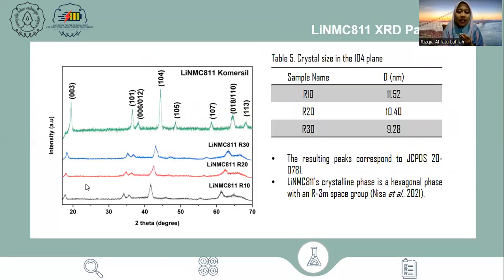The next is the diffraction pattern from the lithium nickel manganese cobalt material. The peaks correspond to JCPDS number 20-0781. The sharpest peak is obtained at 2 theta 41 to 43 degrees. The crystallite size obtained is presented in Table 5. The lithium nickel manganese cobalt crystalline phase is a hexagonal phase with an R3m space group.